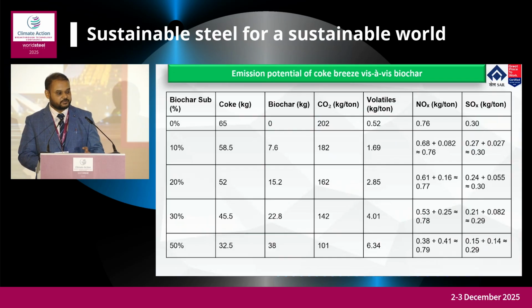So we have projected different values of biochar replacement vis-a-vis the volatile matter, in kg per ton of sinter, which will ultimately go into the ESP and other installations, and NOx and SOx emission in various conditions. We can see that the more biochar addition, the more benefit we get in emission terms. But the production and productivity angle is also considered. So all this data, we have tried for an optimization of having a lower value of productivity loss, however having much benefit of emission potential. So our main study was an industrial optimization.